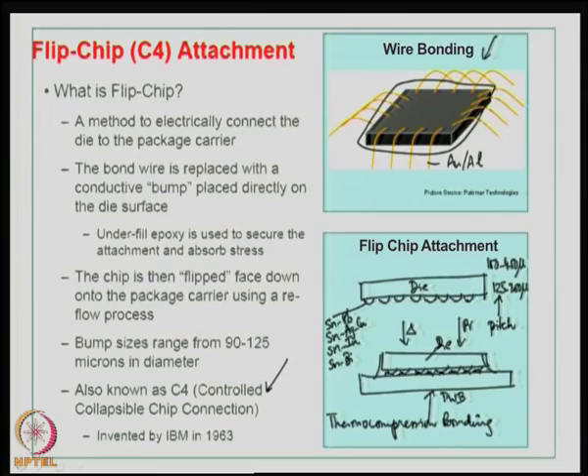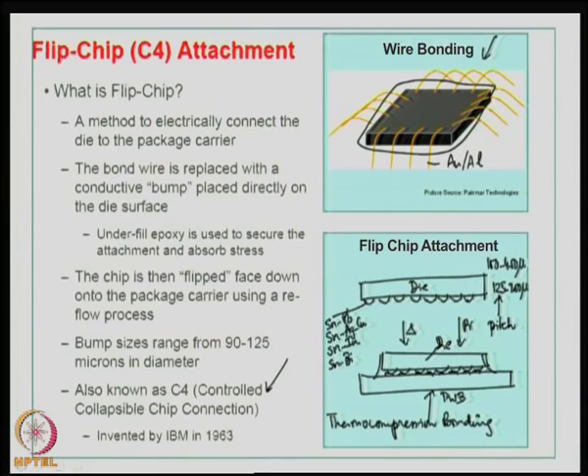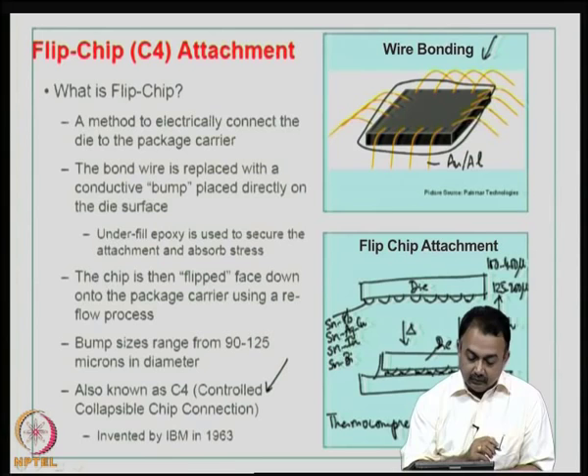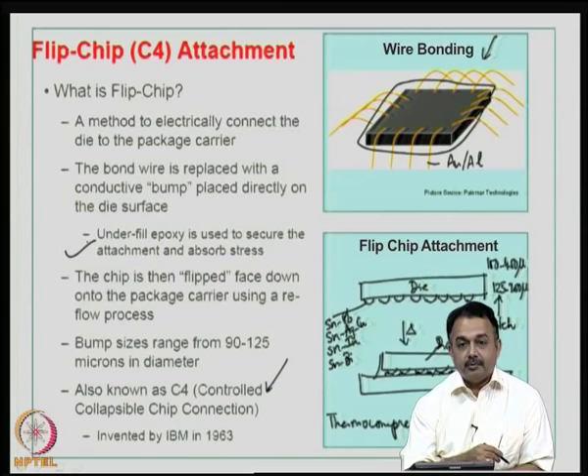The bumping process itself is a technique we are going to look at very shortly. When you use a flip chip, you will have to look at the materials used in the bump because only then can you characterize the reliability of the solder joint. You need to characterize different types of materials used in flip chip. You need a good understanding of the bump material, the substrate material, and the basic thermal mismatch that can happen between the bare die which is silicon and your organic substrate. You can use underfill epoxy to protect the die and the substrate because there is going to be stress when the board is in operation or when the chip is powered up.